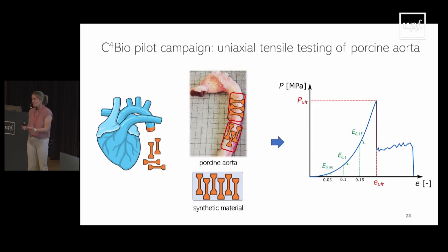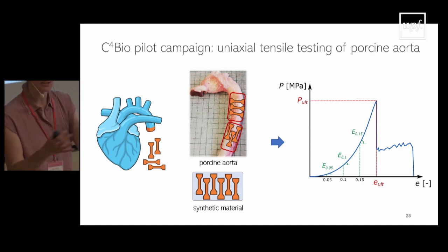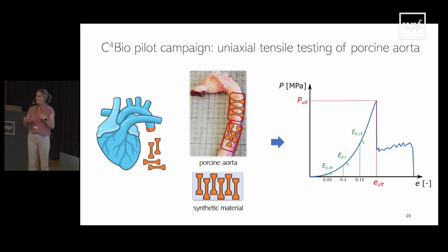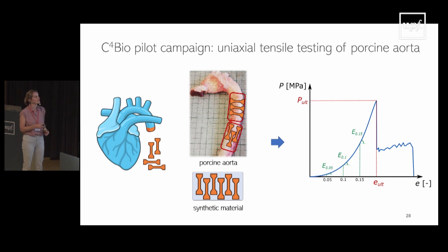So we wanted to start simple. We thought as a warm-up, let's just have all interested participants join, where we all just do a simple set of uniaxial tensile tests. So what we did in our lab at KU Leuven, we went to collect 100 porcine aortas from the slaughterhouse, from the same age, same strain, same storage conditions. We prepared them into samples, so we had a couple of circumferentially oriented samples, a couple of axially oriented samples. We also sent along some synthetic material for comparison and to avoid biological variability. We sent those samples to all the participants around the world, and we asked them to bring back just this simple stress-stretch curve.